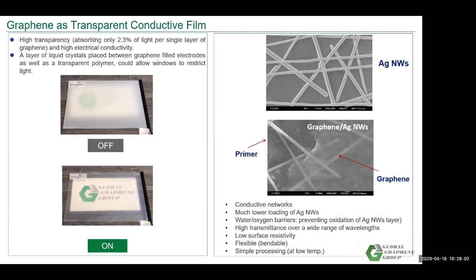In this slide, we give you an example of a window or smart window application. Before you charge it, or before you put the electricity in there, it's like a haze, non-clear sheet. But when you apply electricity, you can see that it's transparent. That's basically using the electrical conductivity of graphene to perform like this. We also combine the graphene with silver nanowire to protect the silver nanowire, which will improve the electrical conductivity tremendously. And with this, in the opposite of dissipating heat, with graphene and silver nanowire, we can even heat it up as a resistor to offer some type of heat. So this is just an example that, despite the thermal management solutions, there are other different aspects of graphene that can be used too.